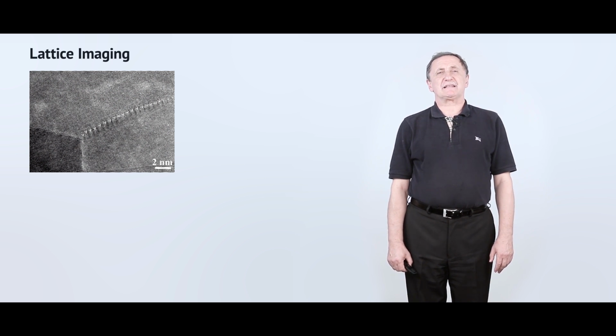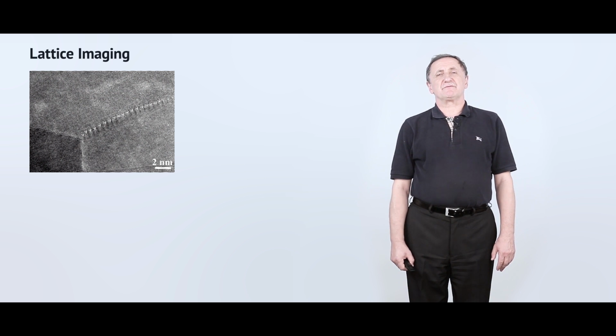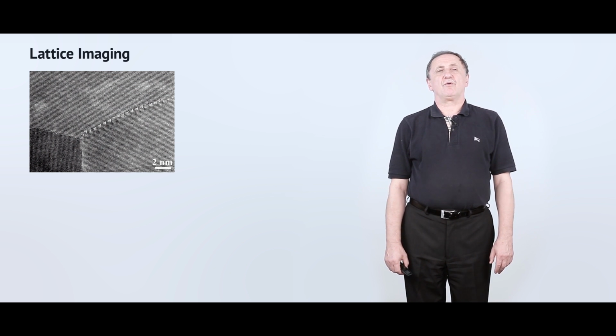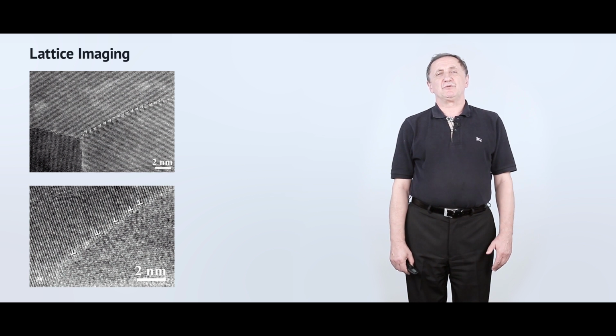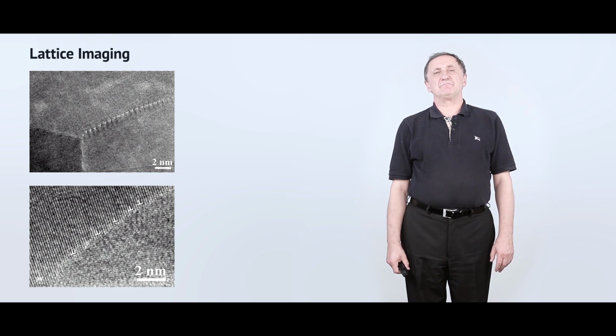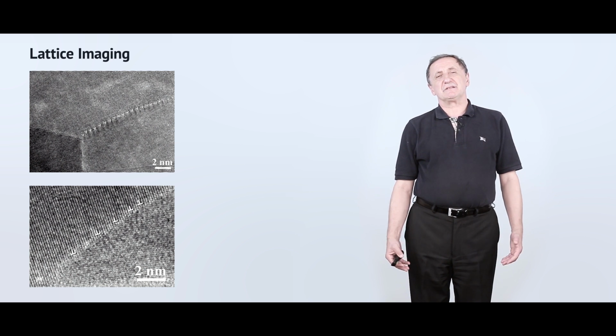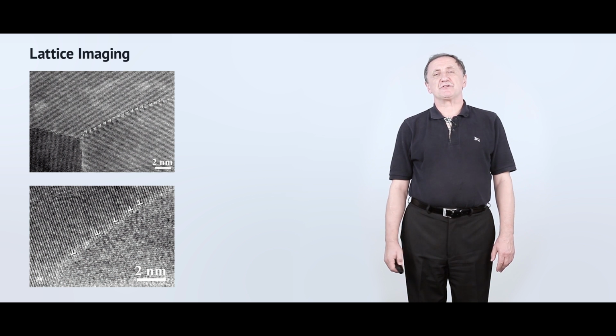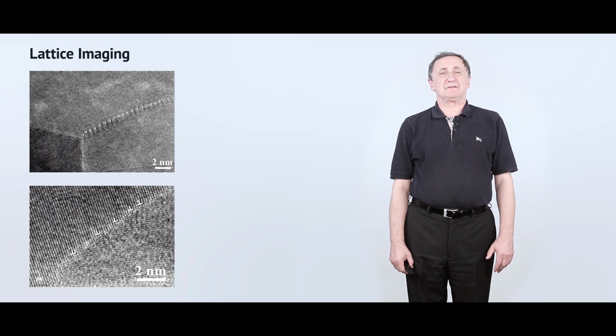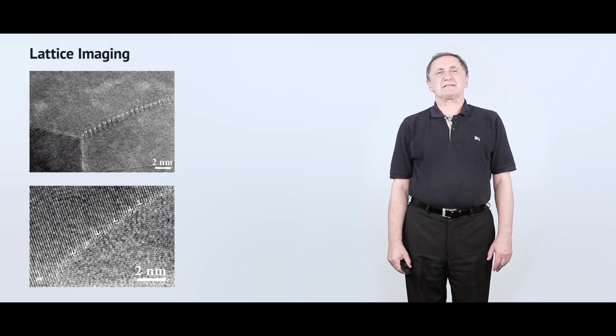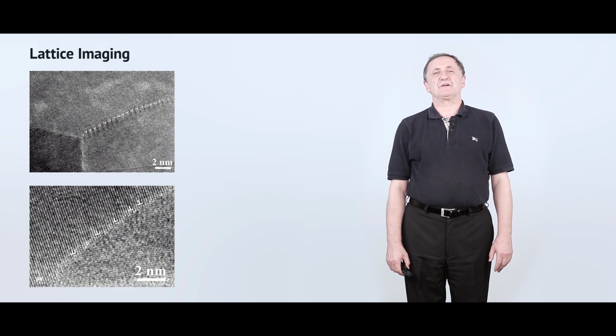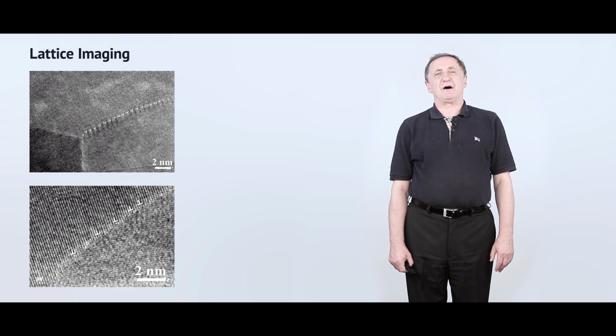If we now try to obtain an image taking into account transmitted and diffracted beams, we go to the so-called lattice imaging mode. On this screen, for example, you can see three grains of nickel aluminide. You can also very nicely see the grain boundaries and different types of defects, dislocations, and even, in some sense, atoms. You can measure the distance between these atoms and draw a conclusion about the crystal structure. So lattice imaging is atomic scale imaging.